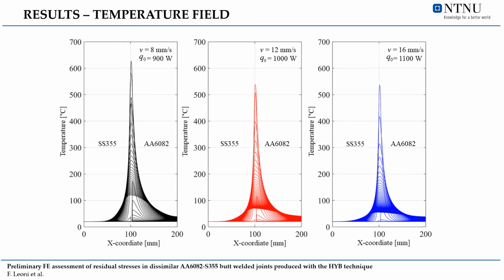These graphs here are a comparison between the temperature evolution considering a cross-section of the plates taken in the middle length of the welds. As the welding speed increases, the temperature drops, but not as much as would be observed in fusion welds. This is because here the heat input also changes with the welding speed, while in fusion welds it can be set constant. Moreover, a narrower thermal field is observed for higher welding speed.